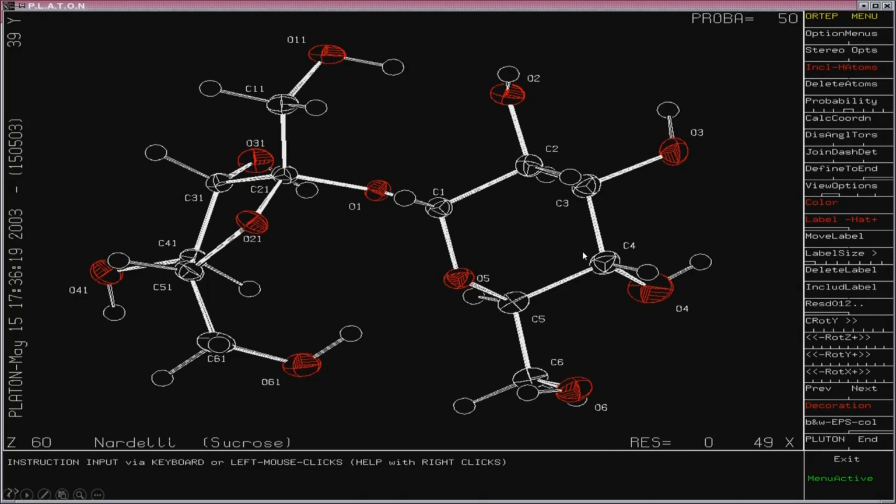So, those hydrogen positions therefore can be actually fixed at that particular distance and angle which it is making with respect to the atoms. For example, this hydrogen atom which is coming out of this carbon atom, the oxygen atom is going down. So, the stereochemistry around this particular carbon is tetrahedral. So, we have now the 3 directions fixed. The 4th direction can be now given to the hydrogen atom, and at the corresponding distance, a normal C-H distance is about 1 angstrom. So, we take 1 angstrom from there and fix the hydrogen position.